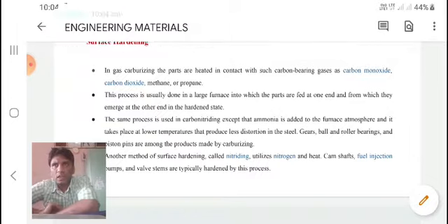So the rate of diffusion is dependent on the alloy and carbon potential of the atmosphere. So care must be taken to ensure that only sufficient carbon is available in the atmosphere at one time to satisfy the take-up rate of the alloy to accept the carbon atoms. In practice, this is defined in a carbon potential set point profile which runs concurrently with the temperature cycle.